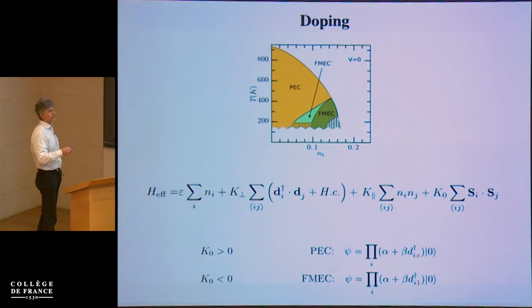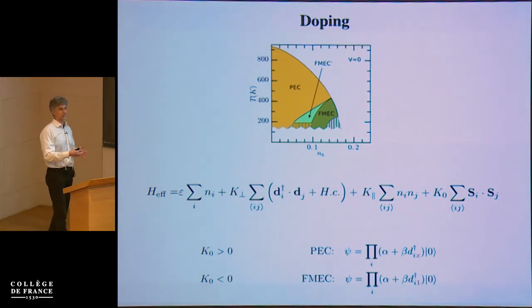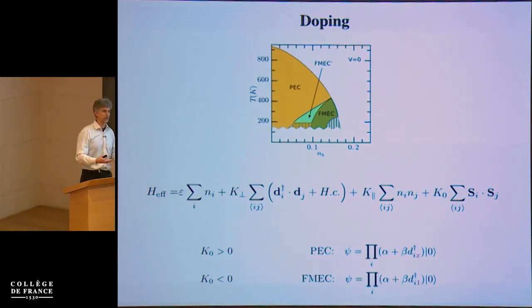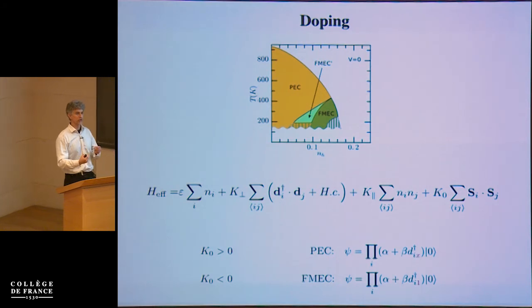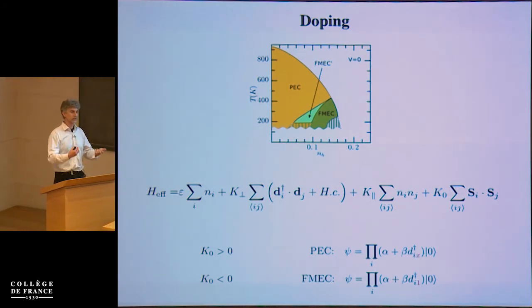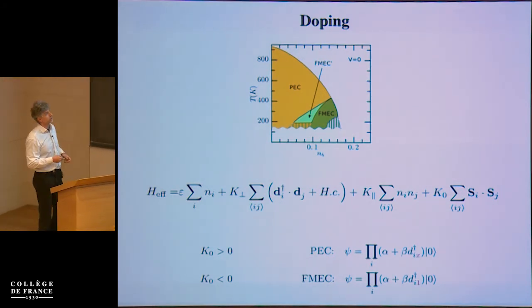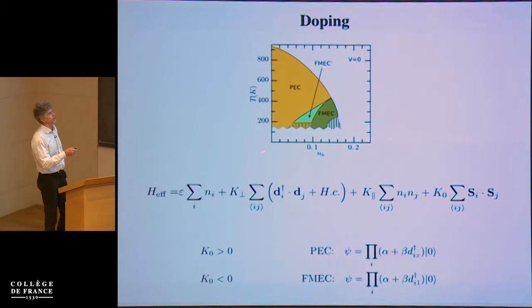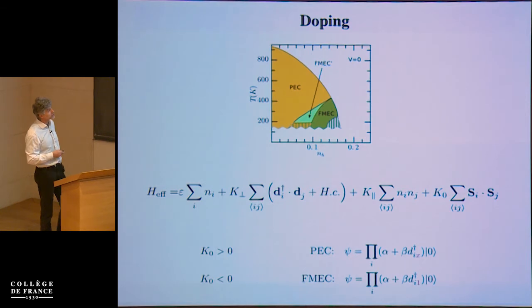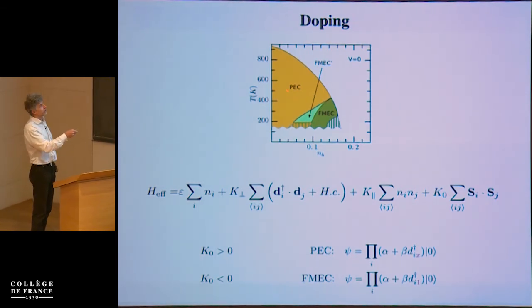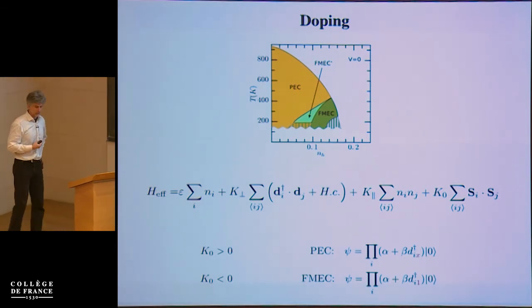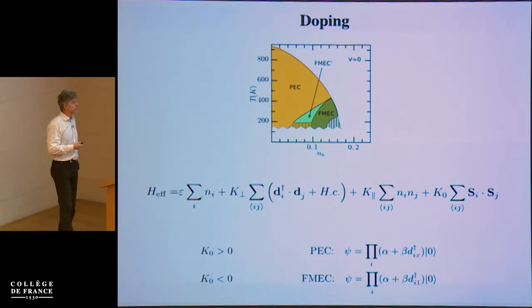Now, if we introduce some doping, we can see the same effect that Eisenstein and McDonald saw experimentally. If you detune the population of electrons and holes, you quickly destroy the excitonic condensation. Nevertheless, there is a finite interval of dopings where the condensation still persists. And interestingly, before we can kill the condensate completely, we actually, by doping, induce the transition from polar condensate to the ferromagnetic condensate. Now, how can we understand it?